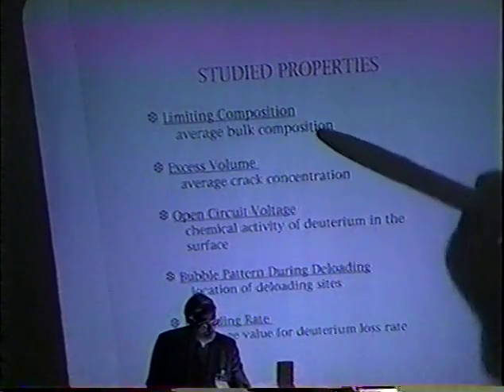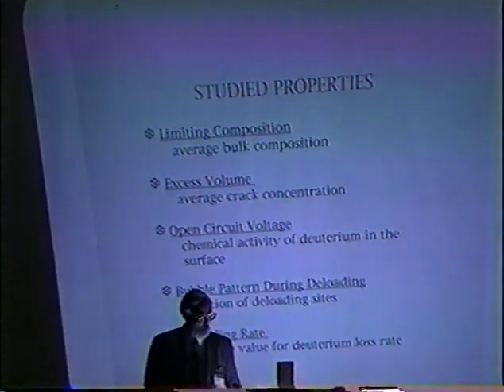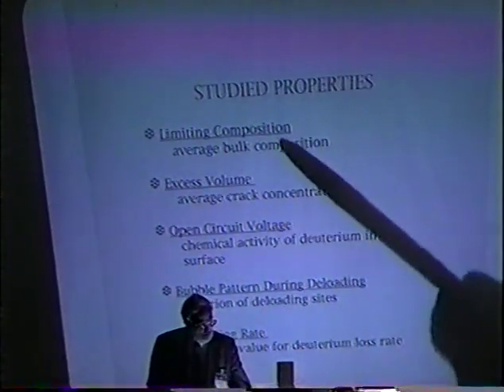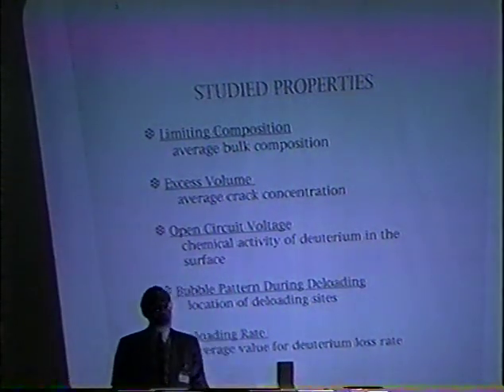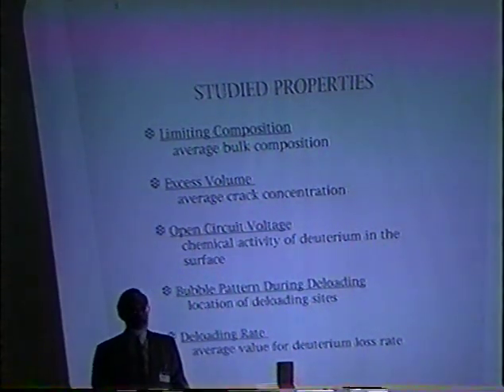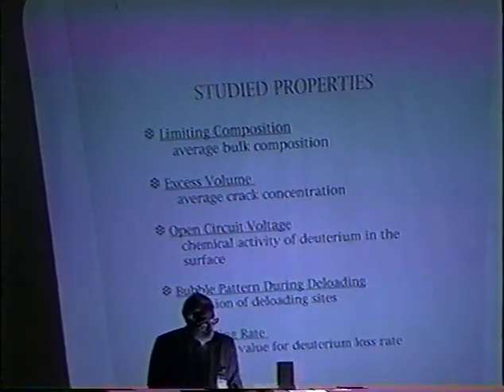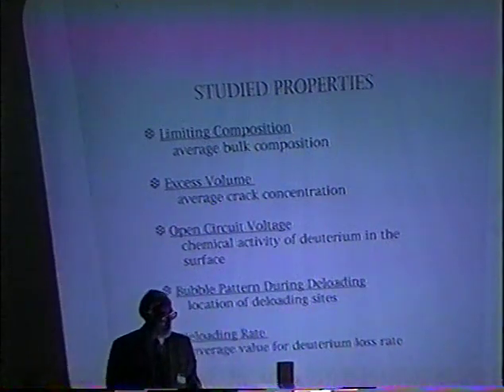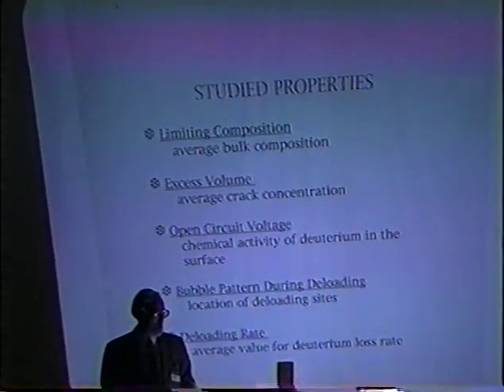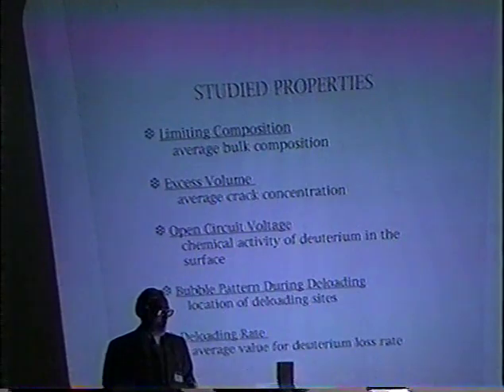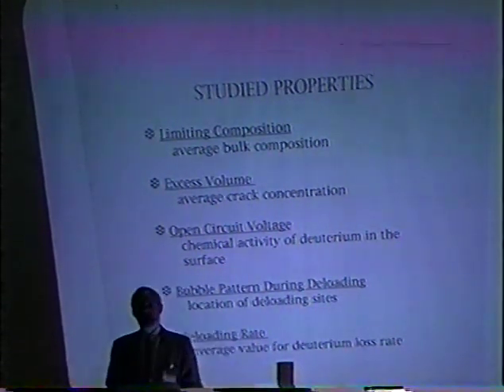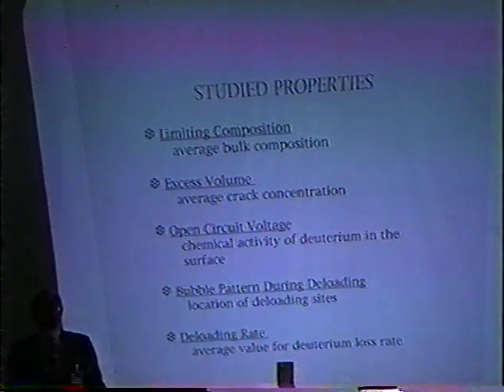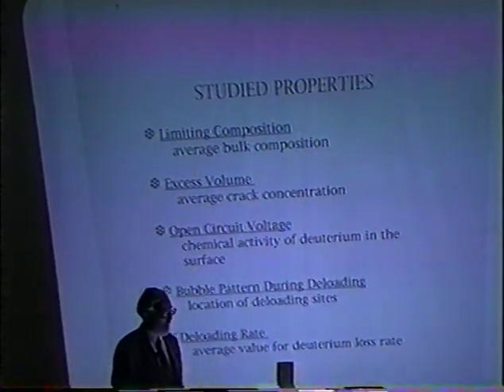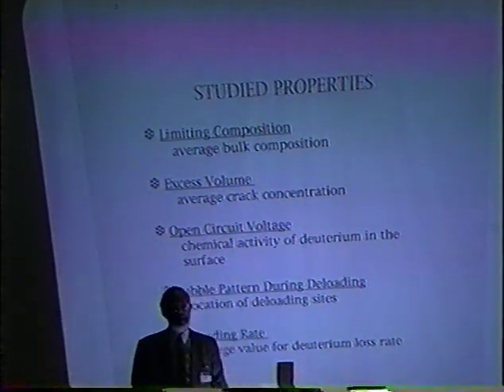But it's the average bulk composition. If that bulk composition does not get above a critical value, you don't get any excess energy. Another one that has not been looked at to any great degree, that Carol, my wife, and I explored at Los Alamos some years ago and has been known for almost 60 years, is the excess volume, and that is related to the crack concentration.